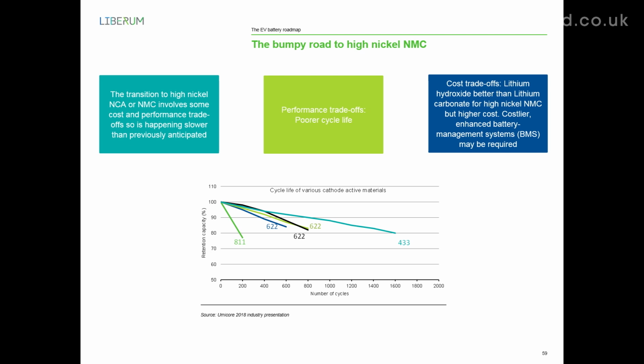Now that's easier said than done, and Asad sort of touched on this. Here you've got a slide which talks about the bumpy road to high nickel. There's a couple of important offsets or trade-offs that are occurring. First of all, cobalt is helpful for stability, and if you take it out of the battery, the cycle life is degraded. And you can see that in the chart here, which shows Umicore's calculations of what the cycle life for different types of cathode chemistries were, admittedly, just over a year ago. And what that's showing is that the number of cycles you could get out of 811 at that stage was somewhere in the region of 1/5 of what it was for current generation materials. And that's obviously a significant consideration.